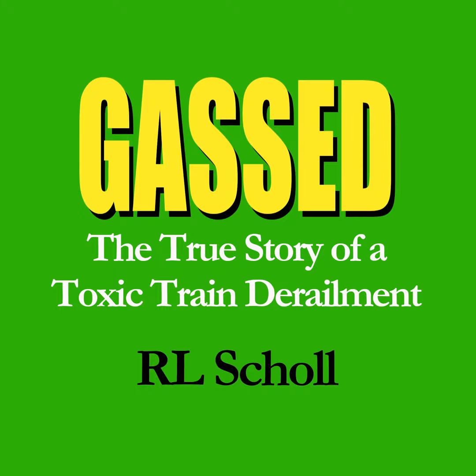In March 1998, Sperry Rail detected 4 vertical split heads in MRL rail within 3 days, ranging from 2 to 39 feet. All 4 rails were A-rail. MRL eventually admitted that even prior to April 11, 1996, they had knowledge of A-rail in Curve 155. How much A-rail lay in Curve 155 became startlingly apparent after the derailment.